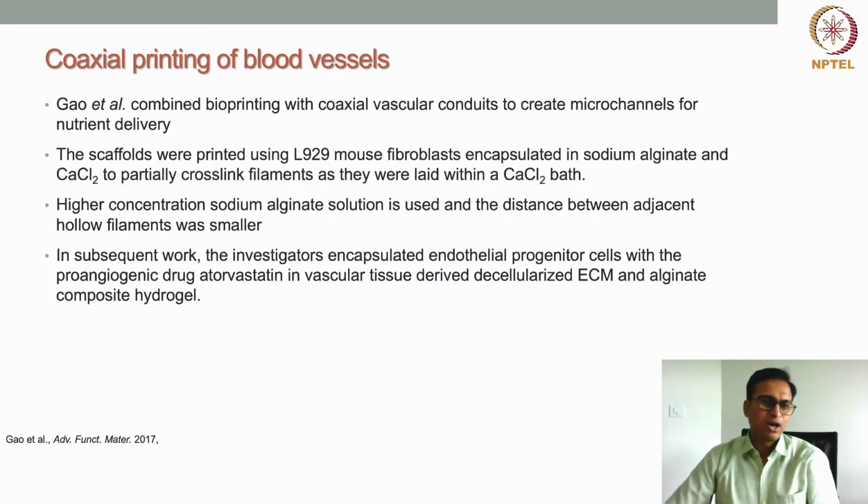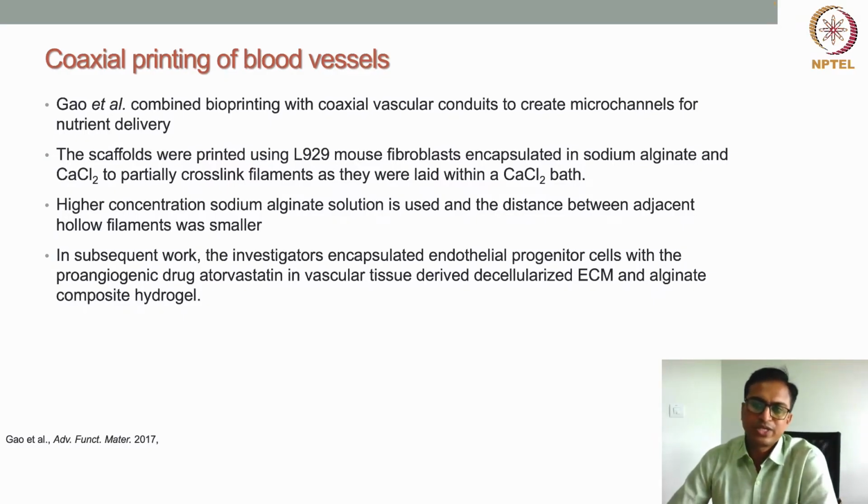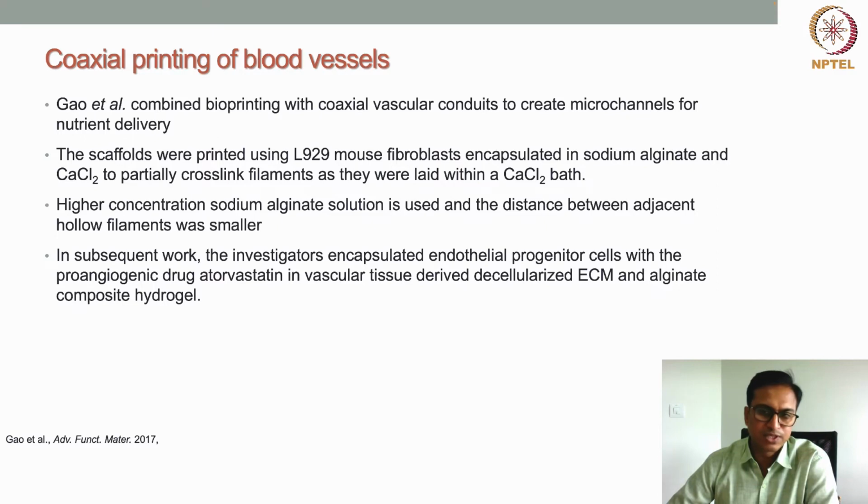Gao et al. combined this coaxial bioprinting of vascular conduits to create microchannels for nutrient delivery. What have they done? They used concentric nozzle extrusion with sodium alginate as the bioink, loaded with mouse L929 fibroblast cells, and filled the inner core of the concentric nozzle, connected to a calcium chloride solution feeder.